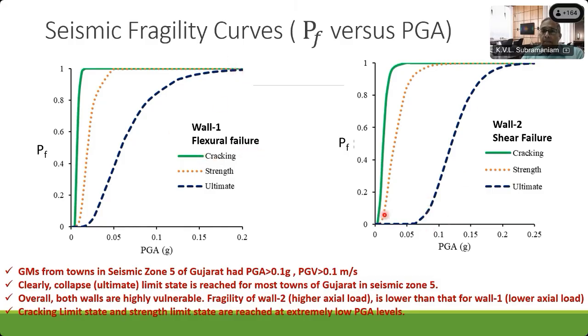The same story would repeat itself for this other wall that actually fails in shear. You find that at very small values of PGA, the walls would be cracked or they would have reached their capacity limits. And by about 0.2 or so, essentially all the walls would have exhibited failure. Now, the ground motions from the towns that we had in zone 5 of Gujarat had PGA greater than 0.1 G. So we were basically sitting somewhere around here to the right of this.